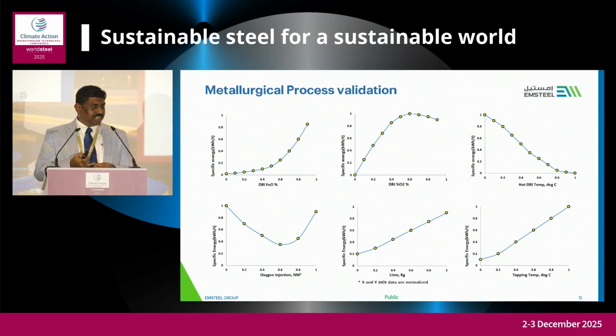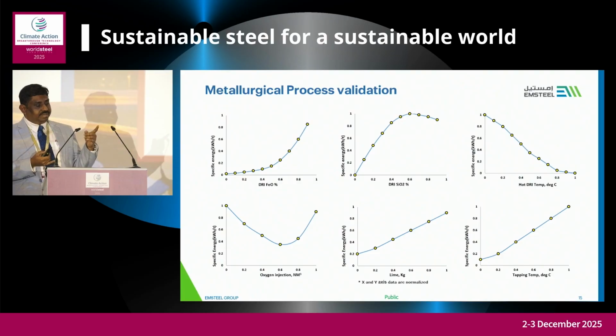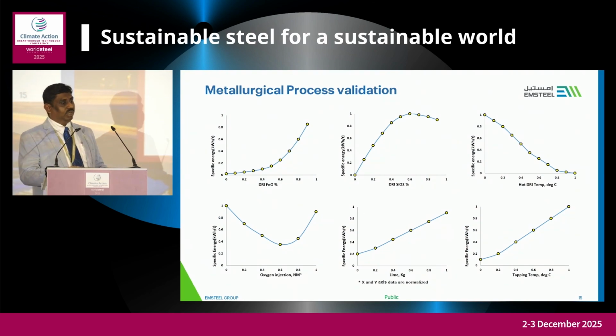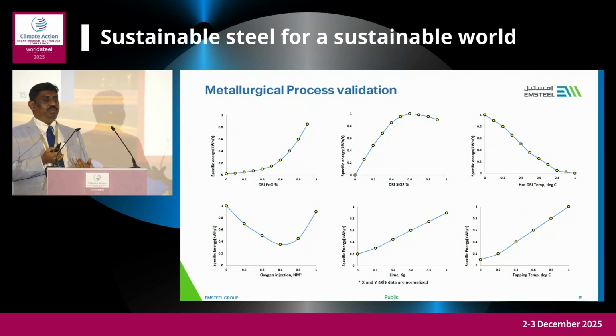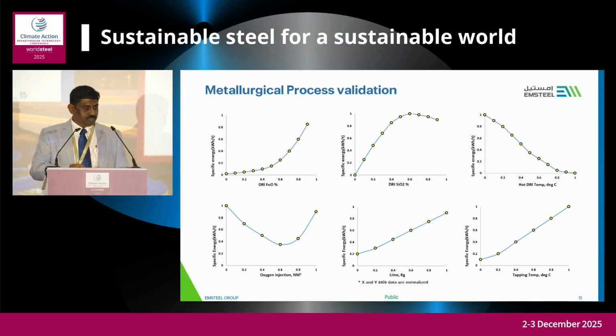Whereas in the oxygen injection system, if you see, this is a plot where after some time it has a negative impact on the process. If you are putting in excess oxygen, it has a negative impact. It reduces the yield, and it gives more oxygen ppm, tap oxygen, which impacts the ferroalloy consumption. So that is negative. The model is capturing the physical phenomena of the process.